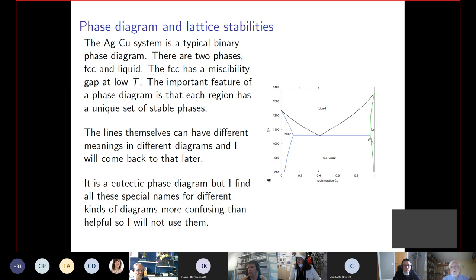And silver and copper don't like to be together, so they separate into two. They have the same crystal structure, but they don't mix. So you have a two-phase region in the solid state with a silver-rich and a copper-rich FCC phase. And normally you learn a little about phase diagrams when you study material science, because they give you an overview of what is happening when you change composition and temperature. But with the CalPhad technique, you give an equation for the different Gibbs energies, and then you can calculate what would be a multi-component system. And I will come back to how to describe what is called an isopleth diagram and how you can understand that, because isopleths are not really very common in teaching anyway.